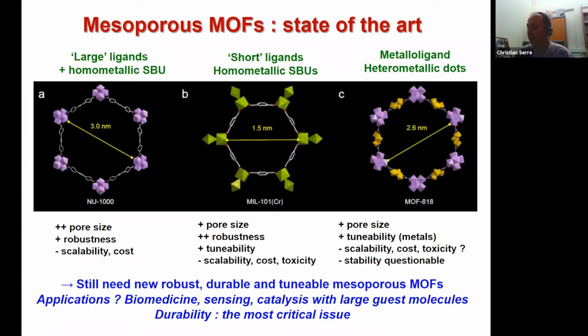The problem is that here you've got two different building units with two different metals. So they have different chemical stability, the copper one being less stable than the zirconium carboxylate one. So the stability is questionable here. And then it is always more difficult to scale up a bimetallic system than a monometallic one, because if you change the scale of the reaction, it is known that even for a single metal, you need to optimize the conditions.